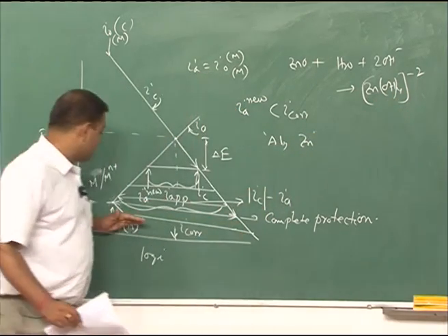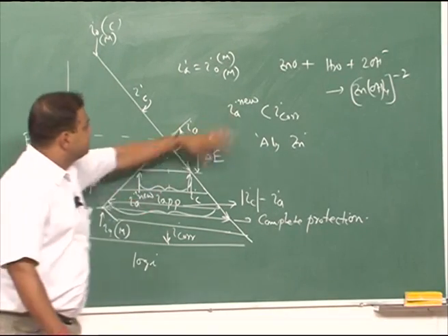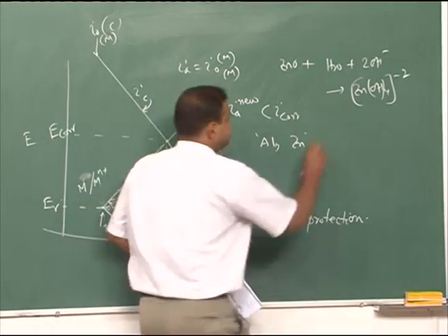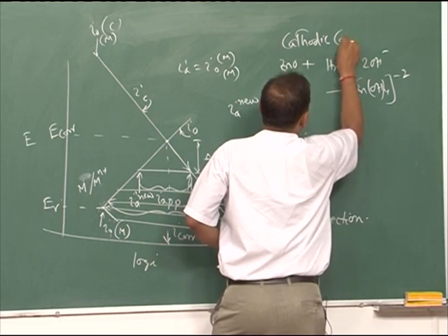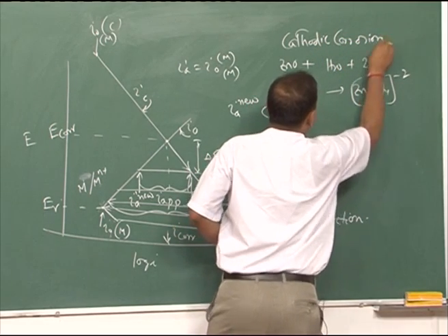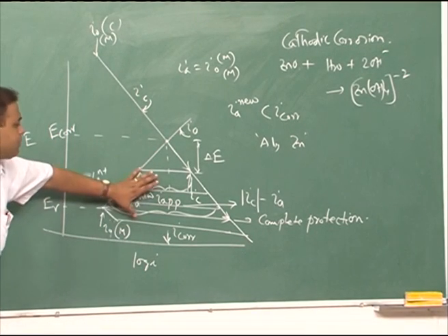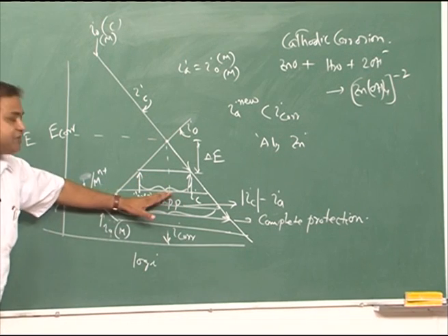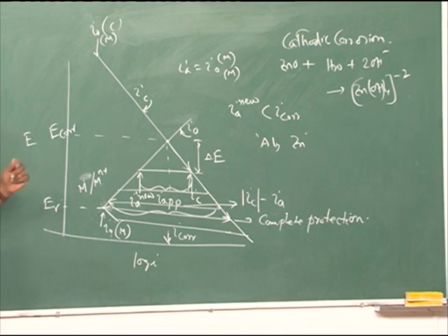So, instead of corrosion protection, we can have corrosion, and this could be termed cathodic corrosion. So, we should not go beyond that. Actually, we should stop in between in order to have a realistic protection at a realistic amount of money to be spent.